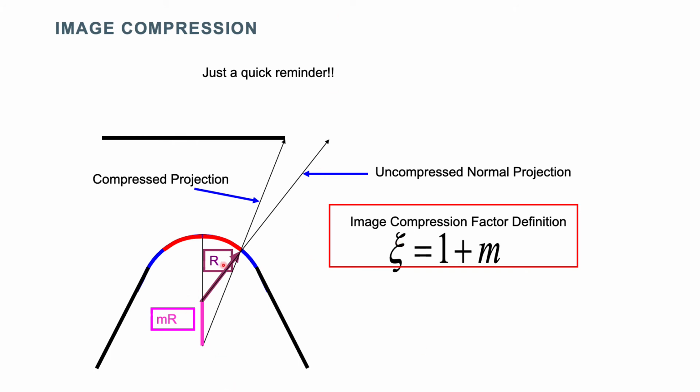So if we had no image compression and the center of the projection was at the center of the spherical cap, we would have a radial projection like this. But actually, the quasi-stereographic projection means that the ions will be coming onto the detector here with some level of compression of the trajectories. So that's what the ICF means.